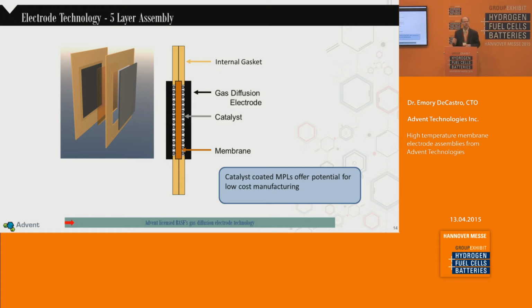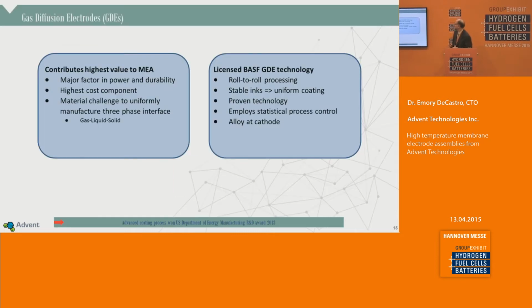The last link in the technology is called the gas diffusion electrode. This is the catalyst coating on the microporous layer. At Advent, we strongly believe this is the low-cost way to manufacture an MEA. If you can think of a stable substrate, a carbon cloth or a carbon paper, going through an applicator in a high-speed machine, laying down a catalyst coat, then from that roll, punching out the pieces you need to make the MEA, you can easily visualize a very low-cost, high-speed system to make MEAs. And so what Advent has done is actually license the GDE technology from BASF, which is a roll-to-roll technology.